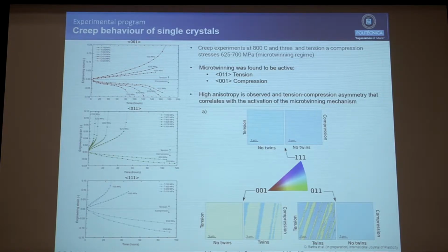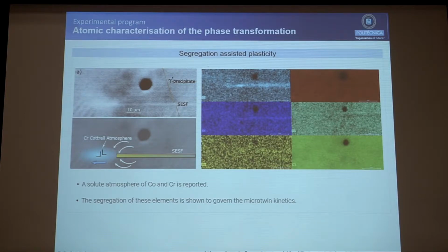So we put one of these samples into a transmission electron microscope at the atomic scale, because we wanted to study what was going on during the deformation. And this is one of the microtwins growing. It's a microtwin embryo, this ledge here. And we found that actually the microtwin was segregated with cobalt and chromium.